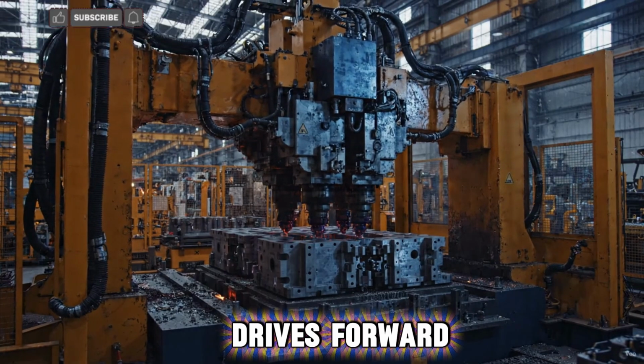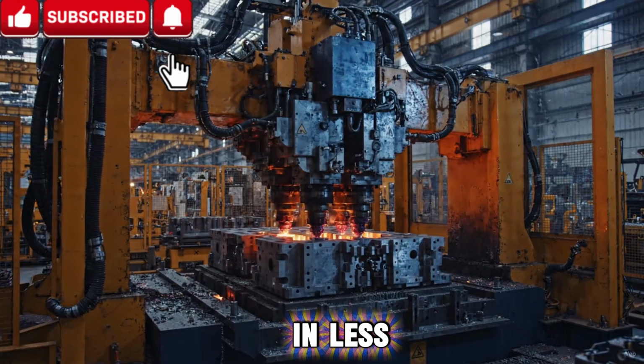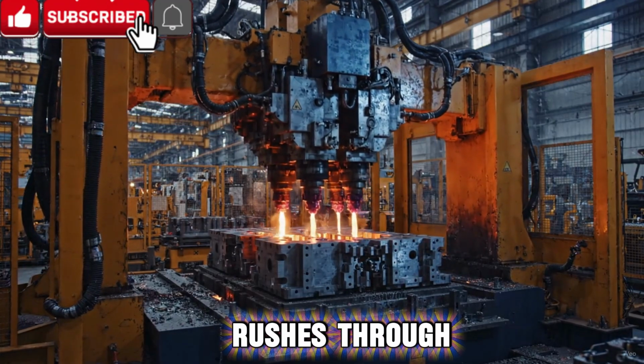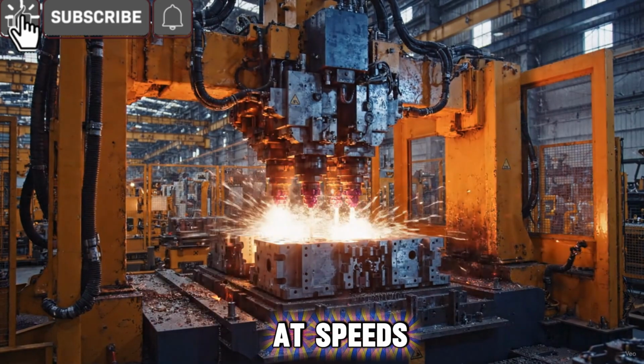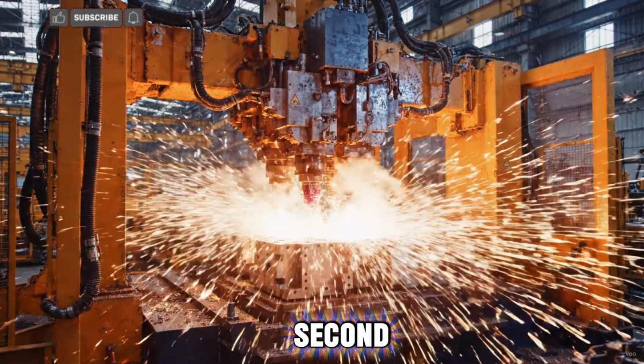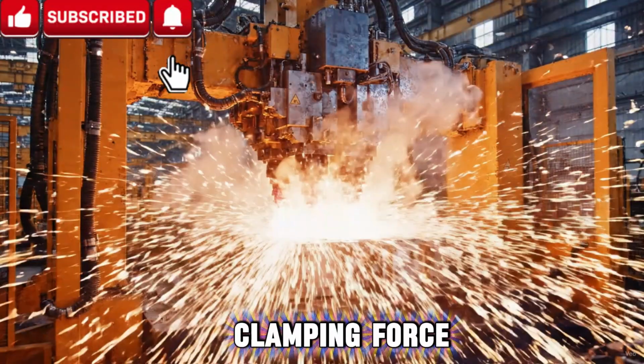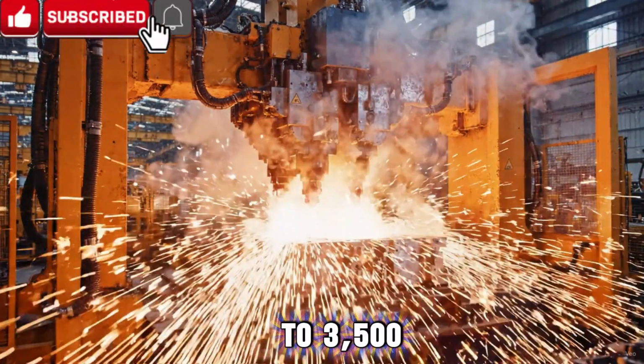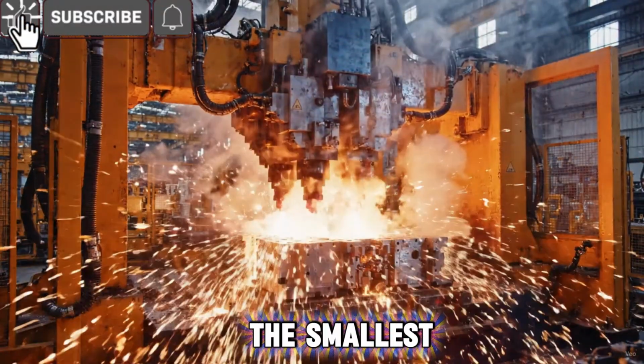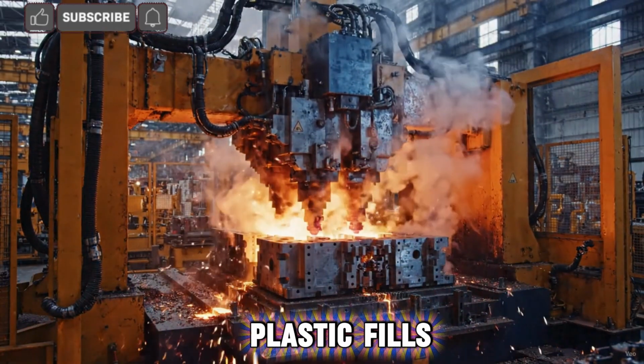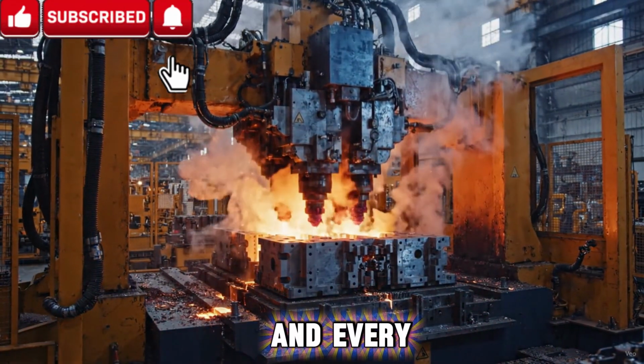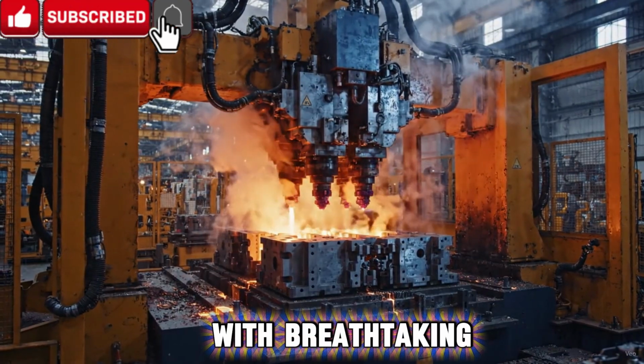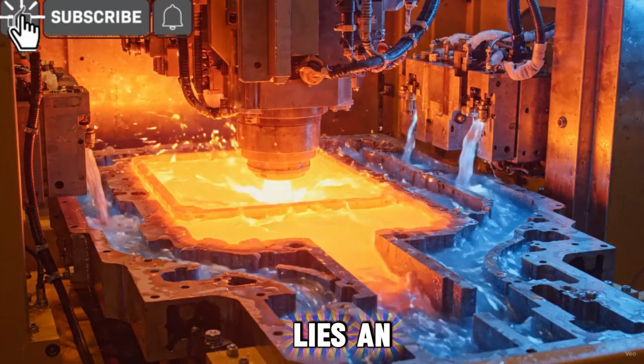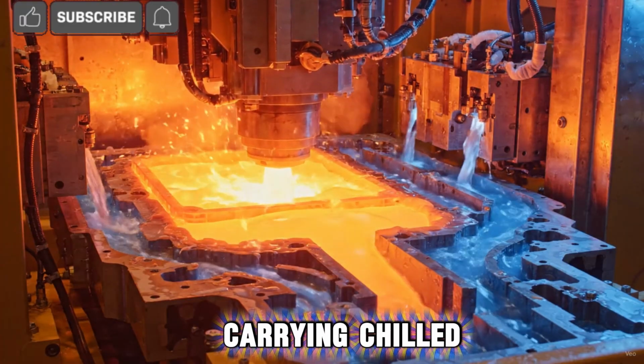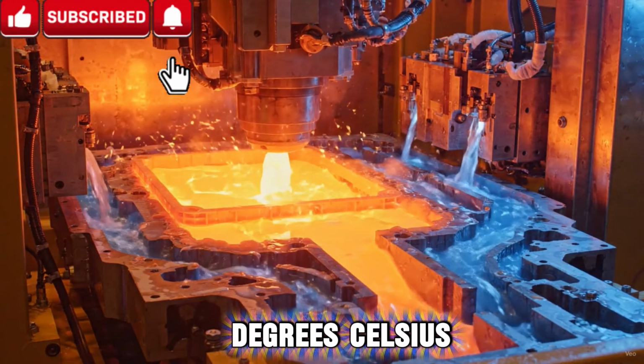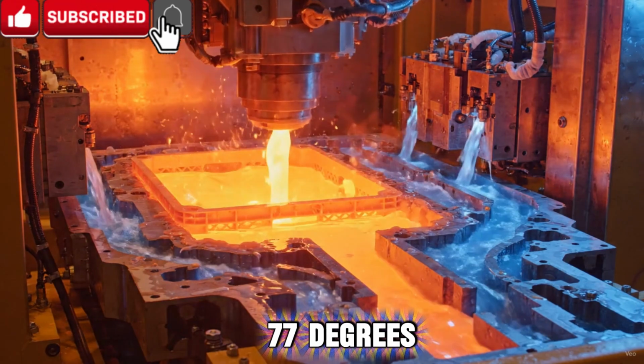Suddenly, the screw drives forward like a giant hydraulic piston. In less than 3 seconds, molten plastic rushes through steel nozzles and enters the mold cavity at speeds reaching 300 millimeters per second. The mold closes with an astonishing clamping force of 1,500 to 3,500 tons, preventing even the smallest leak. At this moment, liquid plastic fills every corner, every rib, and every handle of the future crate with breathtaking precision. Hidden inside the mold lies an intricate network of cooling channels carrying chilled water between 15 and 25 degrees Celsius, 59 to 77 degrees Fahrenheit.